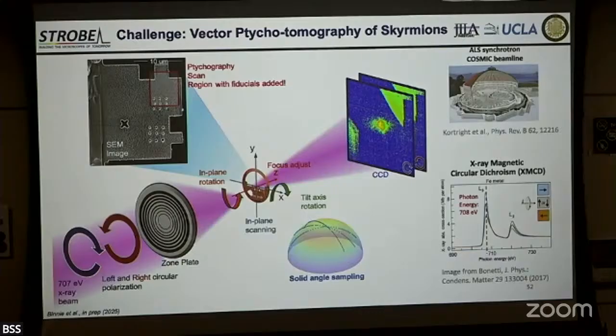This also is a 4-year-long effort, which is trying to image the spin texture in a skyrmion sample. The reason that sample is much harder than the metal lattice sample is that the skyrmion sample only has magnetic contrast. The other sample had a textured nickel metal lattice that gave rise to the frustrated magnetic texture, and we had the actual metal lattice to do all the tomographic alignments. The COSMIC beamline keeps getting better and better, but the way we had to do these experiments, because we were the first group to try this, is you have to take the sample out and put it back in as you tilt. So you're never right in terms of the axes.